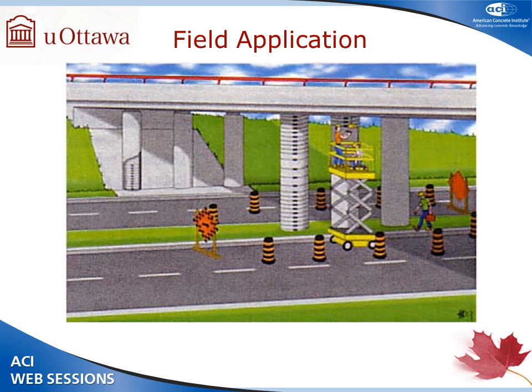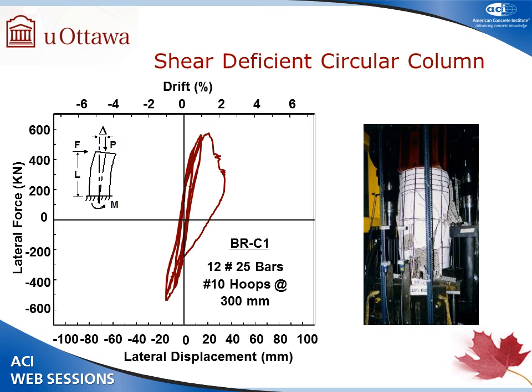I suspect it would go very quickly, and then you can do either rapid repair or retrofit before or after an earthquake. Some of the test results here: you see a shear deficient circular column, which was able to go up to 1%, and there was a sudden failure after that. We had 25 millimeter bars, and this is a 600 millimeter diameter circular column, and we used 10 millimeter hoops spaced at 300 millimeters to reflect the pre-1970s bridge practice in North America.